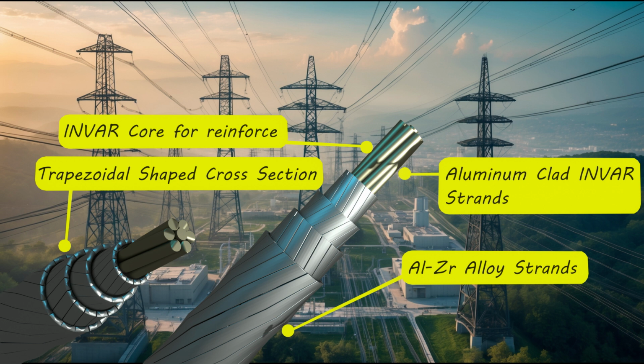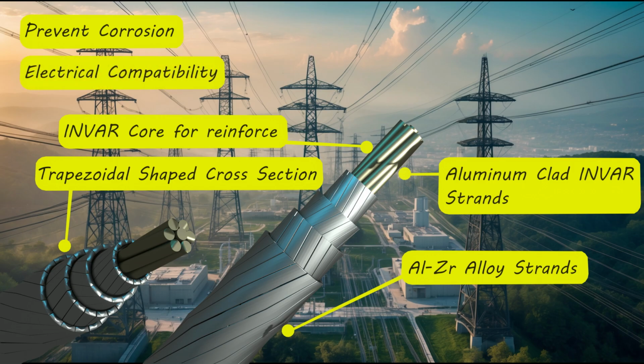Aluminum cladding or coating is applied on INVAR to prevent corrosion. This is because INVAR is not very corrosion resistant on its own. Aluminum cladding improves electrical compatibility with the zirconium aluminum alloy strands of the conductor. In other words, it improves the electrical interface with the surrounding aluminum alloy strands. Aluminum cladding minimizes galvanic corrosion between dissimilar metals like zirconium aluminum alloy and INVAR.